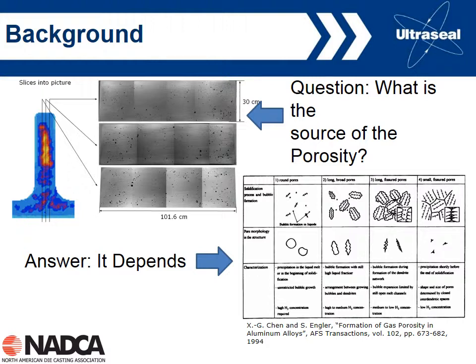But if you look at the first column here, this is very high hydrogen concentration. The pores are forming very early in the solidification process. We only have a very few grains forming, and therefore the pores are spherical. As we move to the right, we're talking about lower hydrogen concentrations, and therefore the pores are forming later in the solidification process, and they become more jagged in column 2, very jagged in column 3, and basically we have the final solidification here. And so porosity is going from smooth to jagged based on the hydrogen concentration, based on when it forms during the solidification process. Early in the solidification process, they're spherical. Late, they're jagged. But these are all coming from gas.